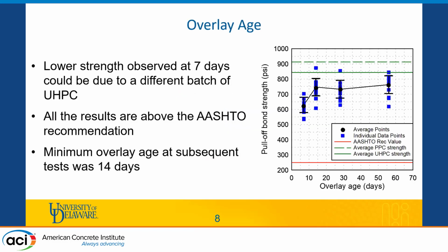So the second thing here is the overlay age. Since polyester polymer concrete is a fast curing material, we weren't expecting a high variation between the overlay ages. And that's what we notice from the 14, 28, and 56 day ages, with an average between 700 and, maybe, 760 PSI. However, the 7 day age is lower than that, approximately 630 PSI.